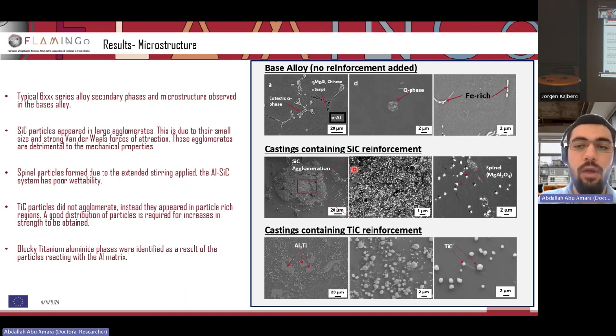With the addition of the silicon carbide particles, we saw that the silicon carbide particles appeared in these relatively large agglomerates. When we increase the magnification on this agglomeration, you can see the individual silicon carbide particles that can be identified. The reason for these agglomerations is because, as I mentioned previously, the silicon carbide particles have smaller sizes than the titanium carbide. So essentially the van der Waals forces in between the particles are stronger, and it's more difficult to break these agglomerations apart or to disperse the particles.